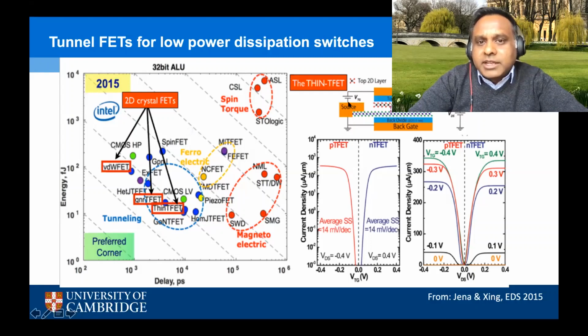But the primary problem has been that it's actually very difficult to have P and N type 2D semiconductors. That is, in contrast to bulk semiconductors where we can add dopants and have a device that runs in accumulation or depletion mode, it's very difficult to dope 2D semiconductors using external dopants, simply because there are just too few atoms in an atomically thin semiconductor to displace one and add another one without disrupting the overall atomic structure. So the approach that one has to take is to engineer the work function of the source and drain electrodes for injecting either electrons or holes into the semiconductor. And that's been a main sort of problem.